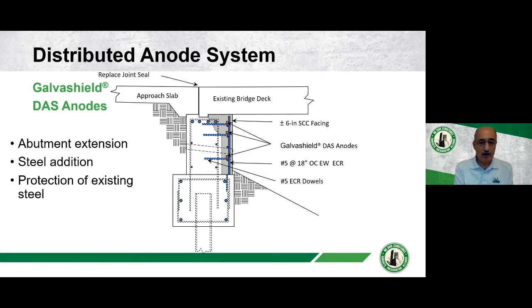And I'm just going to talk about one other system. We call it distributed anode system. All it is basically, it's just long galvanic anodes distributed in a sense that you are distributing the current better, because you can line up your anodes against the steel reinforcement. In this particular case it was for an abutment that had steel added to it, and it was thickened to increase its strength. But of course, you still have your old steel, which is embedded in suspicious concrete. Some of that needed to be repaired anyway. So you need to be protecting your existing steel. So the anodes are placed in such a way to protect that. This is an example of that.